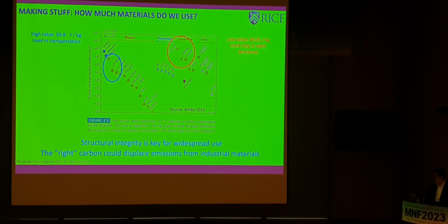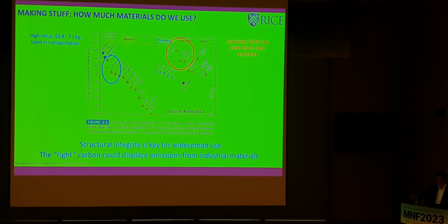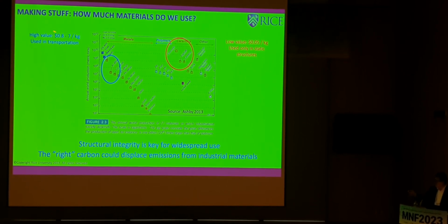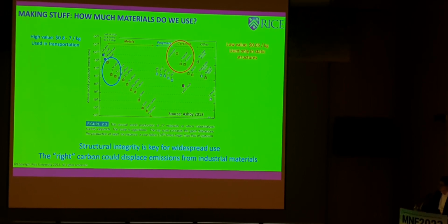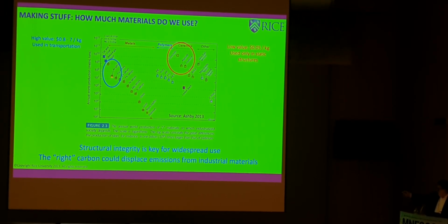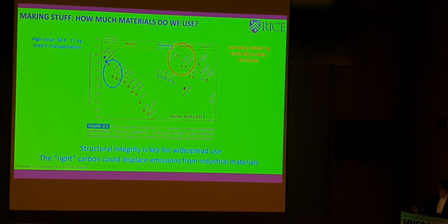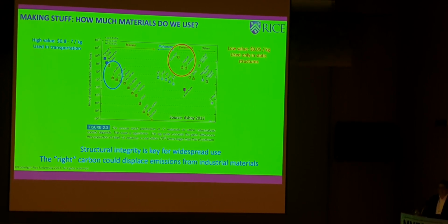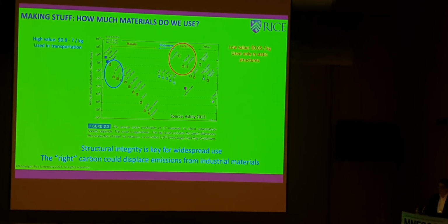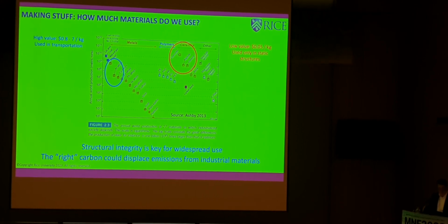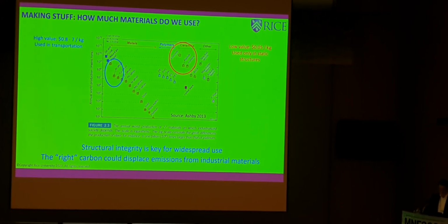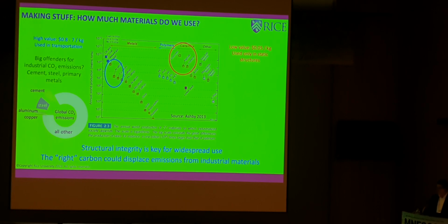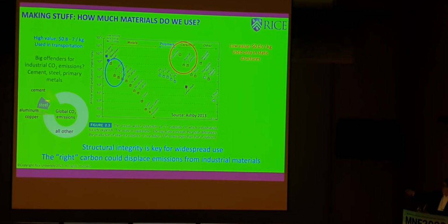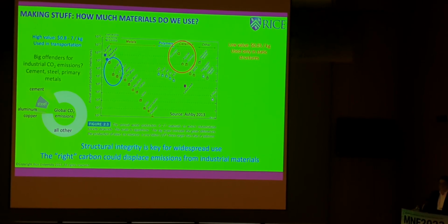But over here, there's much lower hanging fruit, which is metals, and it's because the values are higher. You start at about $1 a kilo for steel, then $7 a kilo for copper, and as you go down here, you get higher and higher. And these are at the low end, right? This is bulk steel, bulk copper. Stainless steel is about an order higher. Wires are even higher.